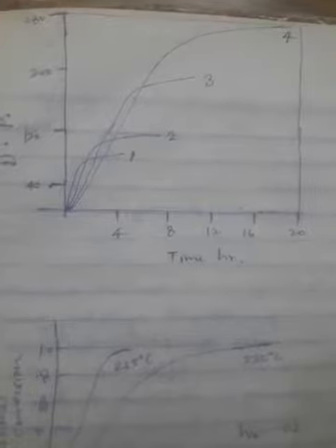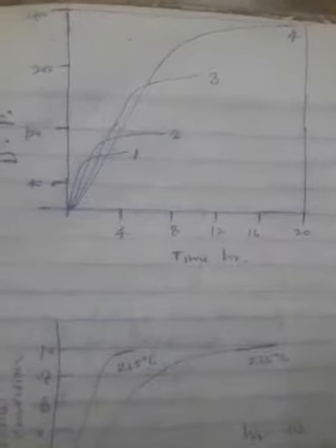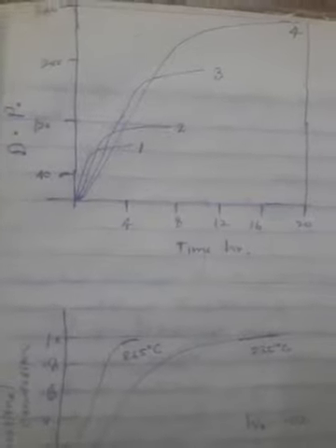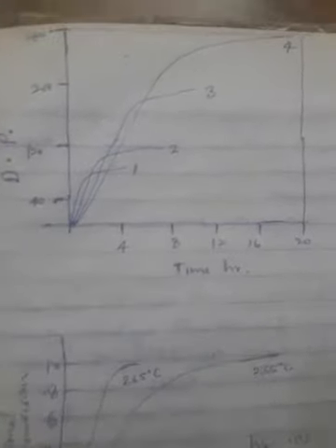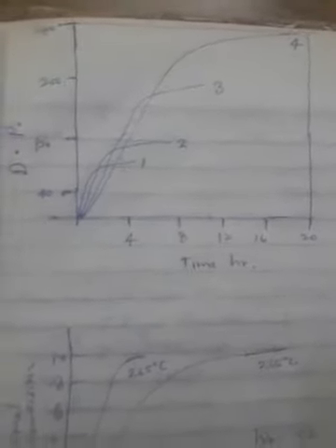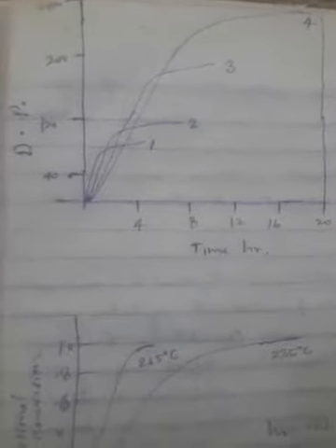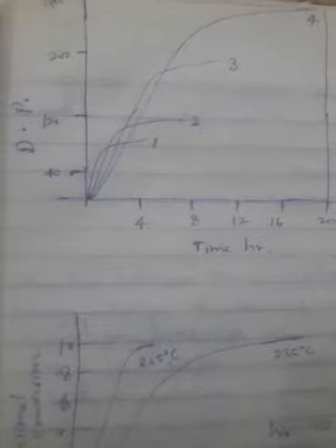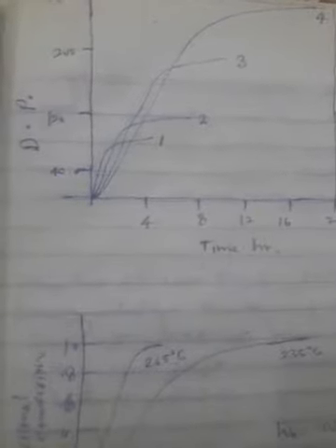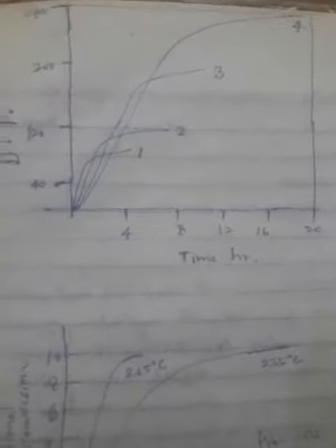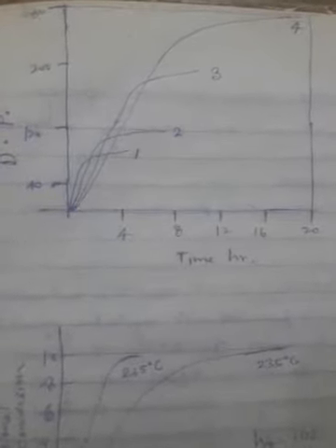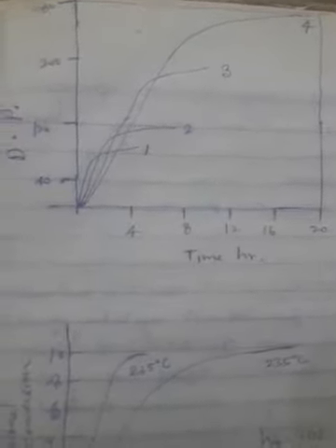The DP for 3 and 4, meaning 2% water, is about 200 or more than 200, where degree of polymerization means the number of repeating units in the polymer. With higher water, no doubt within less time, but the degree of polymerization is only about 80 to 100, very much less.